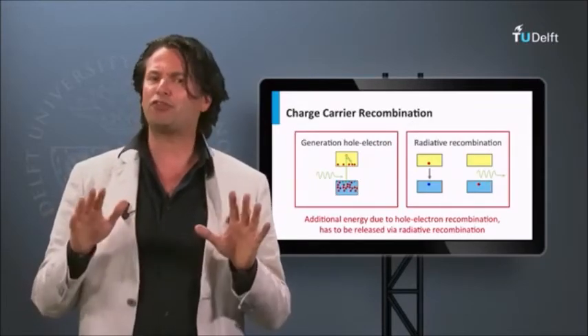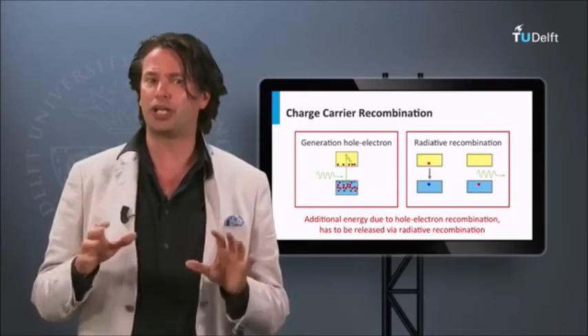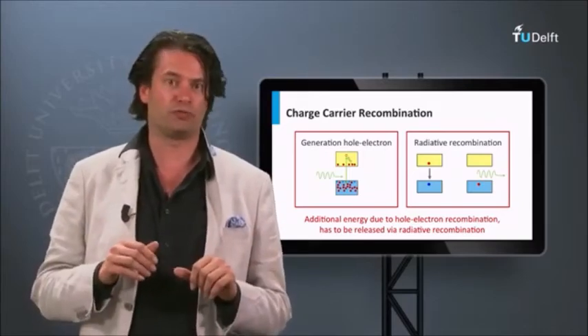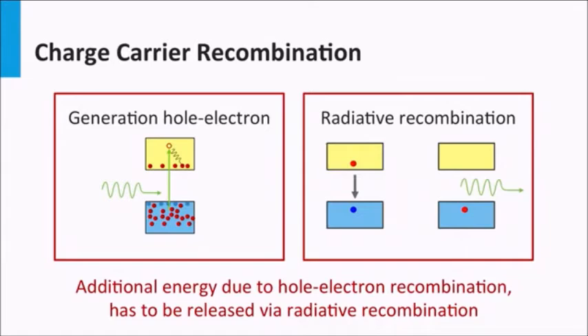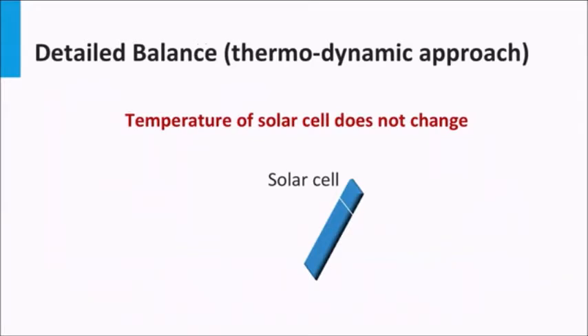Secondly, we have to consider that we do not fully utilize the bandgap energy for the open circuit voltage. As discussed earlier this week, the maximum open circuit voltage is limited by the recombination of charge carriers. In reality, we can have three charge carrier recombination mechanisms: radiative, Auger, and Shockley-Read-Hall. In this case of the Shockley-Queisser limit, only radiative recombination is considered.